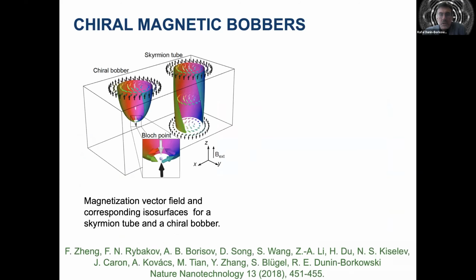The second reason I mentioned is that we sometimes have magnetic singularities. And on the left, there are schematic diagrams which show a magnetic skyrmion tube or string going all the way through a thin TEM sample. And on the right, there is an equivalent object, which is called a chiral bobber, which ends in the middle of the sample at a singularity, which is referred to as a Bloch point.